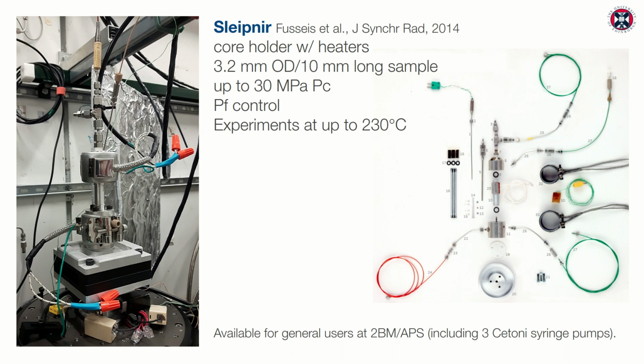What it is, it's a core holder that can have heaters attached, and they are pretty crude band heaters here. It takes 3.2 millimeter OD cylindrical samples. Usually they are up to 10 millimeters long. The cell can support 30 megapascal confining pressure. We can control the pore fluid, and with these band heaters we can heat the entire assembly to up to about 230 degrees Celsius. I show you this image here, which shows the cell in its parts, essentially completely disassembled,